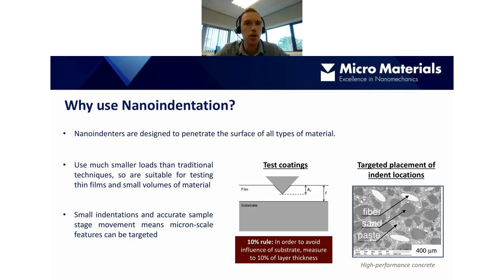So when we're testing coatings in nanoindentation, there's a very general rule, which you may have heard of. It's called the 10% rule, which means in order to avoid influence from the substrate, the indentation depth should be no more than 10% of the coating thickness. So if we have a 1 micron thick coating, then the indentation depth should be no more than 100 nanometers. Obviously that small depth of indentation is not possible with the more traditional test techniques.